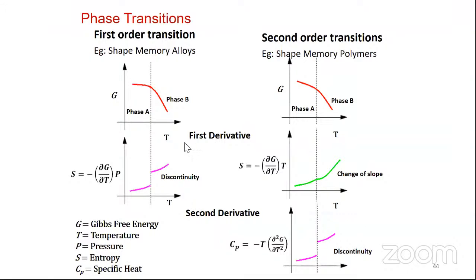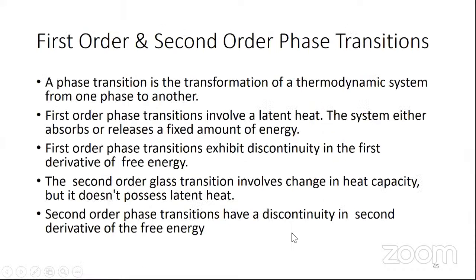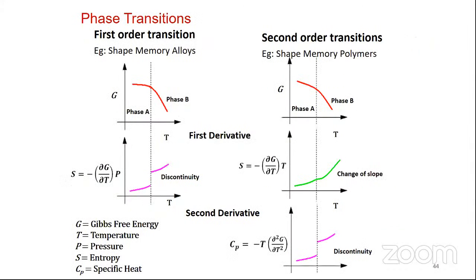If you see the phase transitions in shape memory alloys, it's basically a first order transition, where with the Gibbs energy against temperature there is a shift at the transition. The rate of change of Gibbs energy is nothing but entropy, and entropy has a discontinuity at the transition. Whereas in shape memory polymers, it is not the entropy but the specific heat where you can see the discontinuity. It is a second order phase transition. I am not getting into the details of these phase transitions. Hope you understood from the figure.